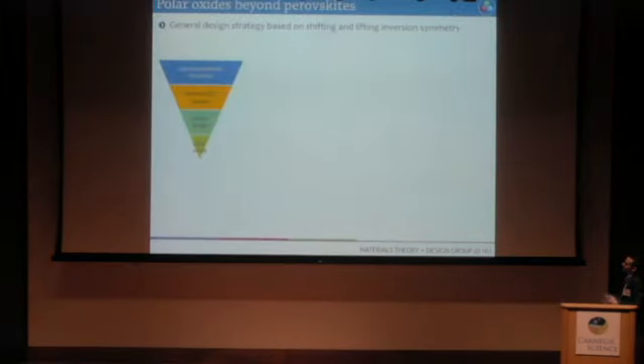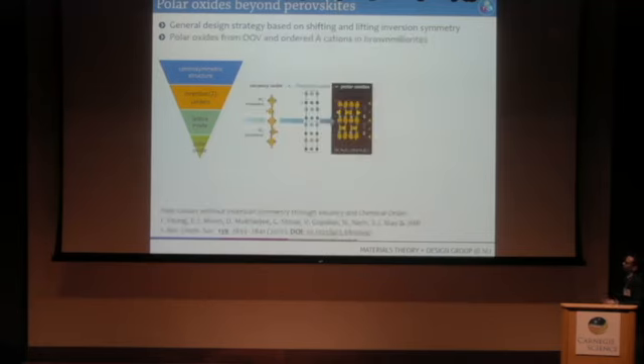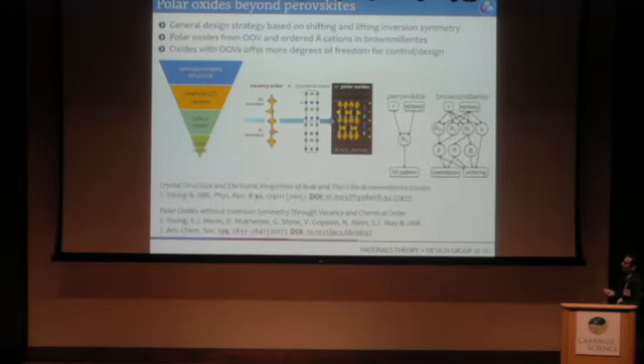Okay. And so what we find then is one can design or discover new polar oxides outside of perovskite simply by applying a design strategy which combines multiple orders, whether it's structural order, magnetic order, orbital order. It's a general effect. You would need to identify the chemistries compatible with those long-range orders. And I showed you the example then for using tetrahedral and octahedral chains in the structures of brownmillerites. So more information can be found in this paper, and the stability of brownmillerites in thin film form is described in this paper. And there's many more degrees of freedom in brownmillerite than in perovskite.